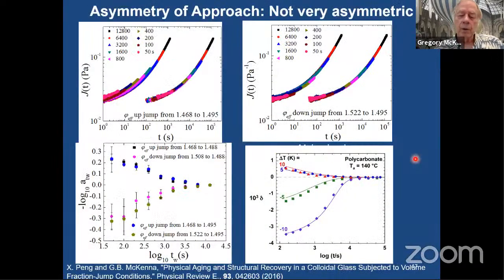But I think a more interesting point is that when we do the asymmetry experiment, so here's the equivalent of the down jump. This is an up jump in concentration. And here's the equivalent to the up jump in temperature. We have a weak asymmetry in this direction and no asymmetry in this direction. Unlike this polycarbonate glass, where we have a very strong asymmetry in both directions. Okay, so that's something that needs to be investigated.